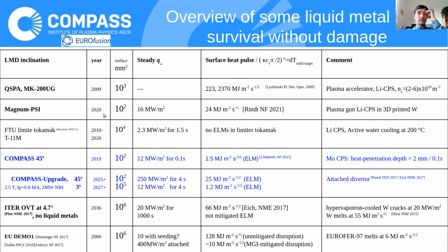In 2020, there was a nice publication, and also before that, on much smaller areas, steady state heat fluxes of 16 megawatt per square meter and quite reasonable heat pulses were achieved on a plasma gun with a lithium capillary pore structure wetted in 3D printed tungsten. On the FTU tokamak, for about 10 years or even more, there were experiments on a pretty large limiter. Because it's limiter plasma, the heat fluxes are an order of magnitude smaller, for relatively shorter time also, and there is no option for heat pulses. And it was demonstrated to survive pretty well at such large fluxes. Even the influx of lithium into the plasma, or even tin later, was found interesting.